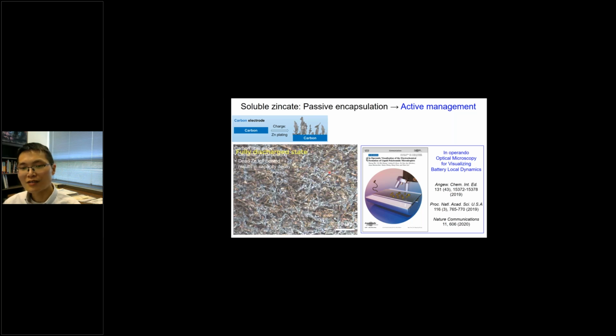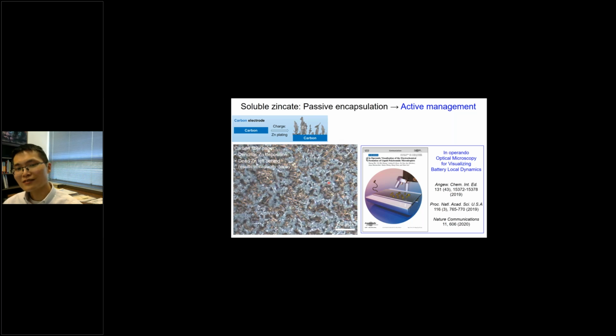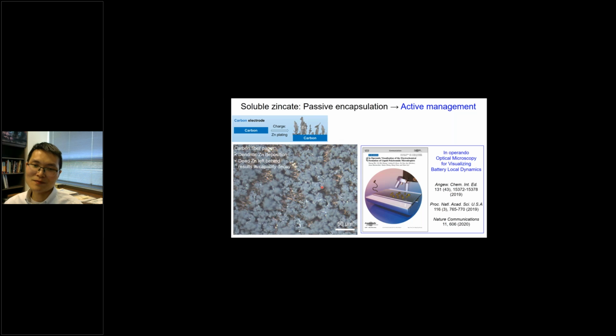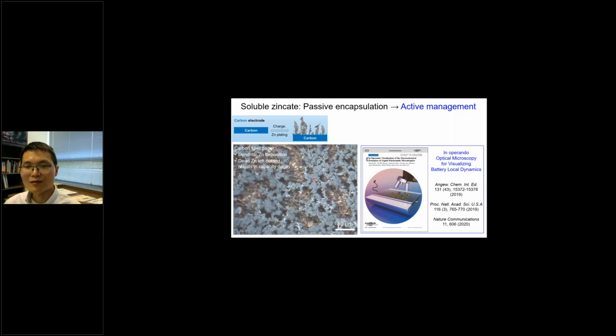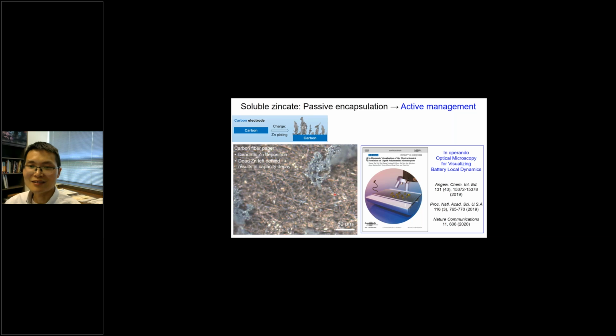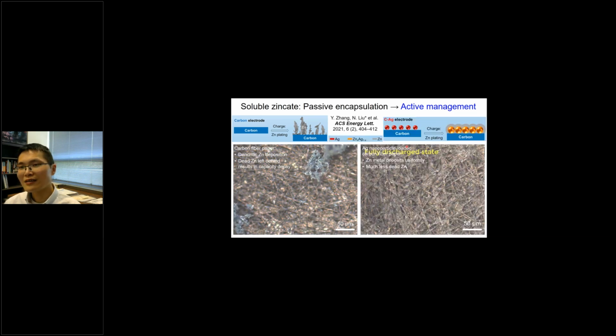The third example is that we still cannot keep 100% of the zinc species inside the shell all the time. So if a little bit escapes, can we actively bring it back into the shell? This is active management rather than passive encapsulation. We did imaging to see how the zinc plating happens. You can see it's very dendritic, and it doesn't grow uniformly. And when you strip, some of it will peel off and detach and become dead zinc and never react. So what we did was add a layer of silver nanoparticle seeds onto this substrate.